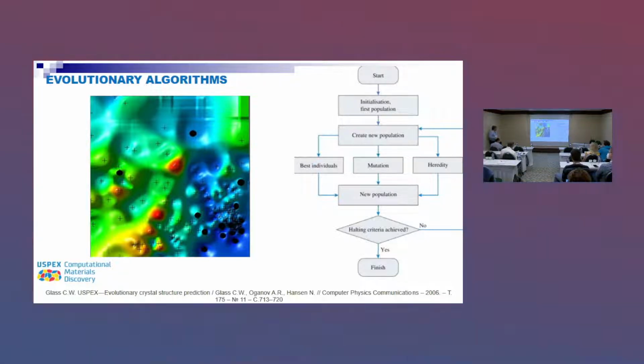And we can have many different local minima, like here, and then we want to calculate all the local minima. It means that in principle, the system can exist in this local minimum for a very long time, until it can go to the ground state, at least at low temperature. And we can consider if it's possible to have a semiconductor state with low energy, and if we can have the transition.